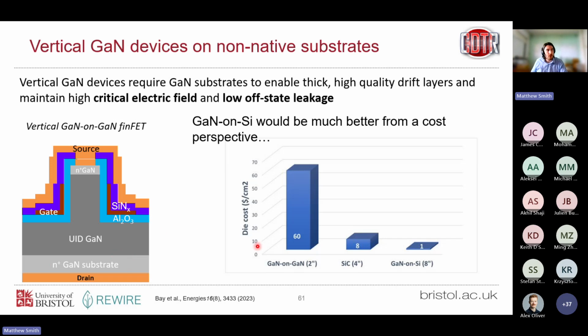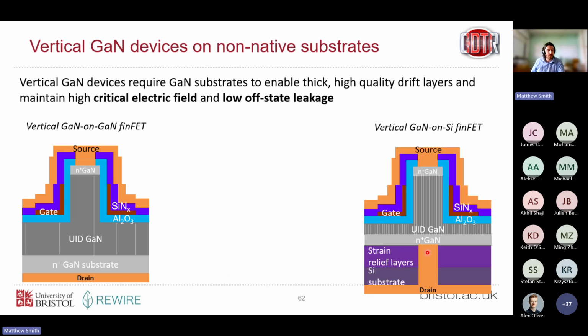Problem there is that from a cost perspective, I don't necessarily believe these numbers, but it's from this reference here. Certainly the scaling is accurate. We see much higher cost per area for GaN on GaN compared to GaN on silicon. So if we could achieve vertical GaN on silicon devices with good performance, that certainly would have a huge cost benefit.